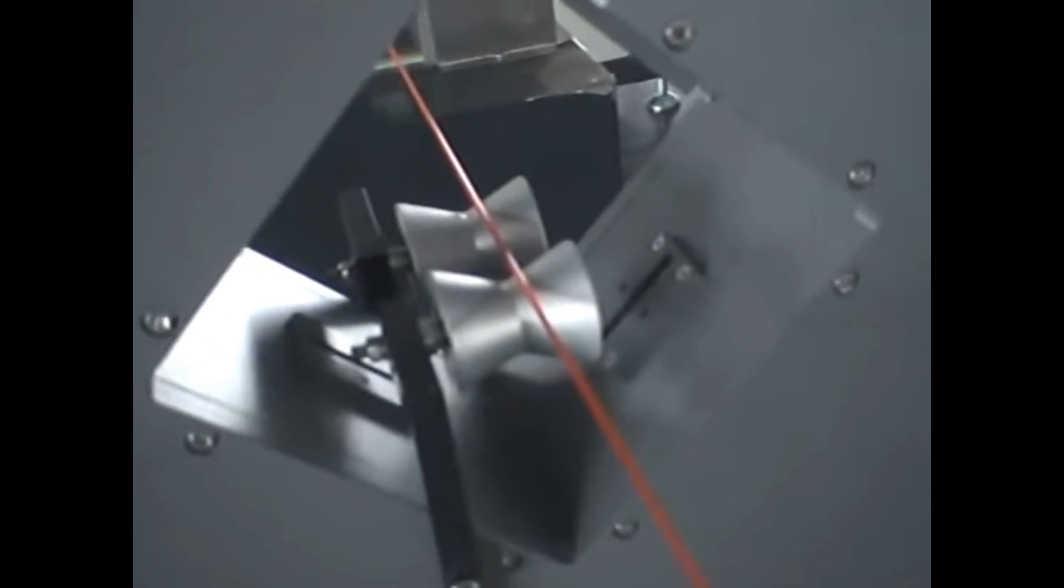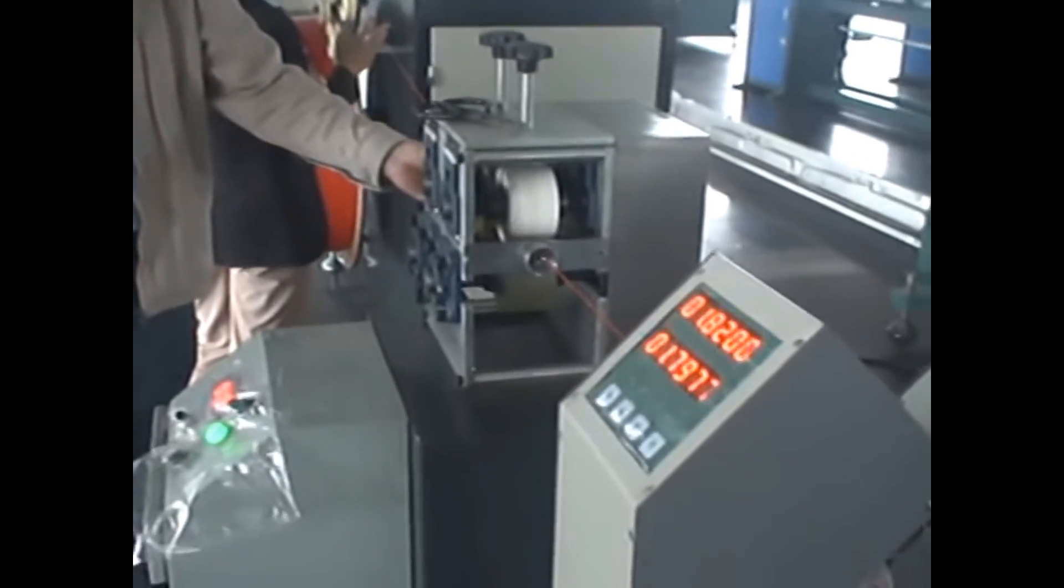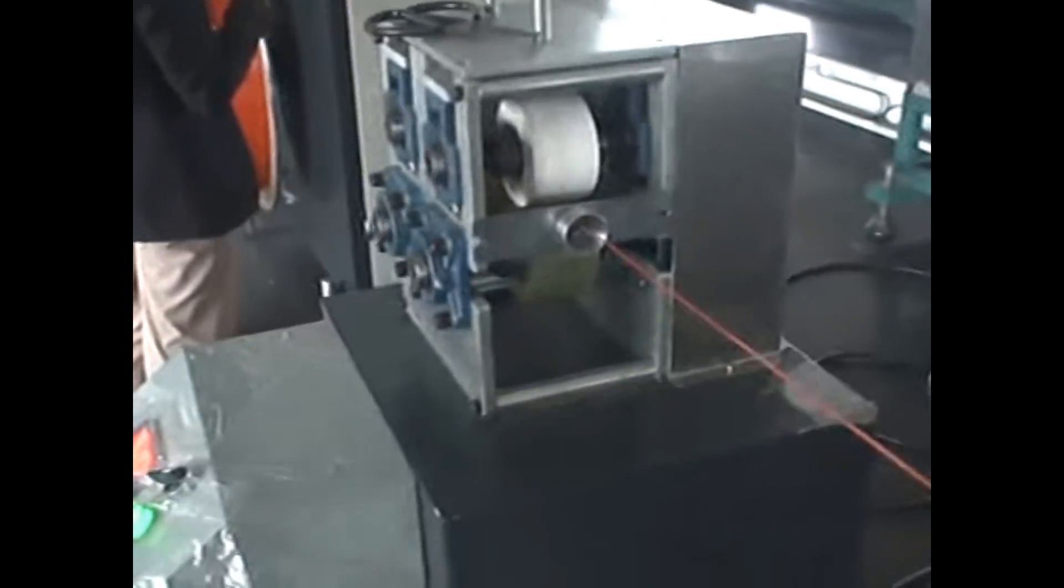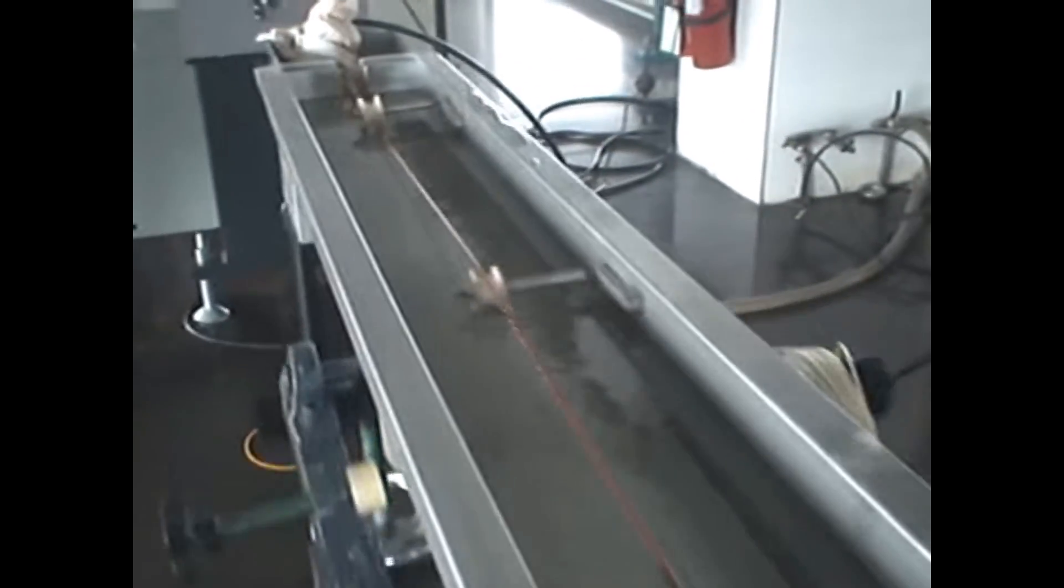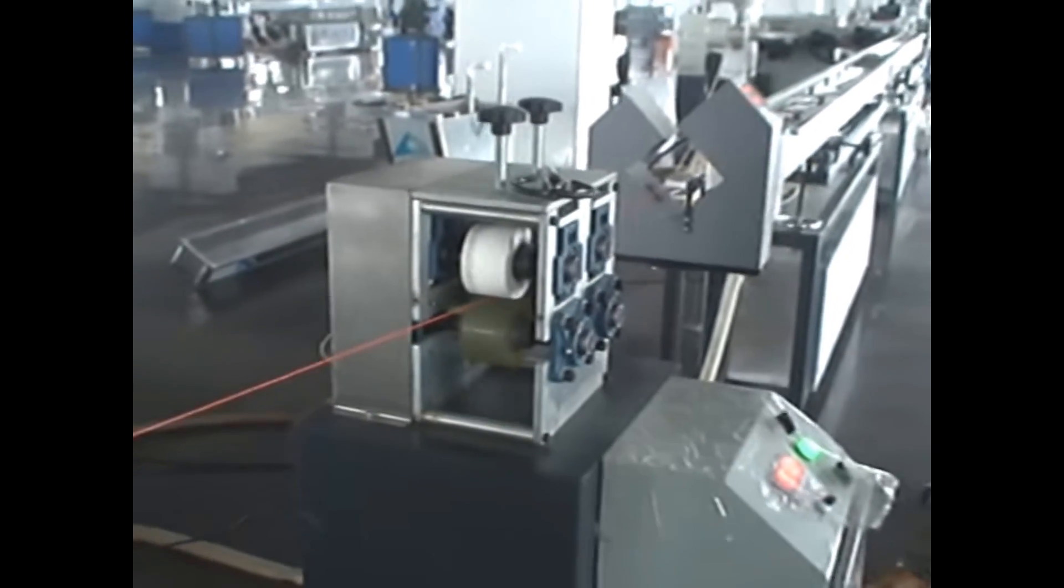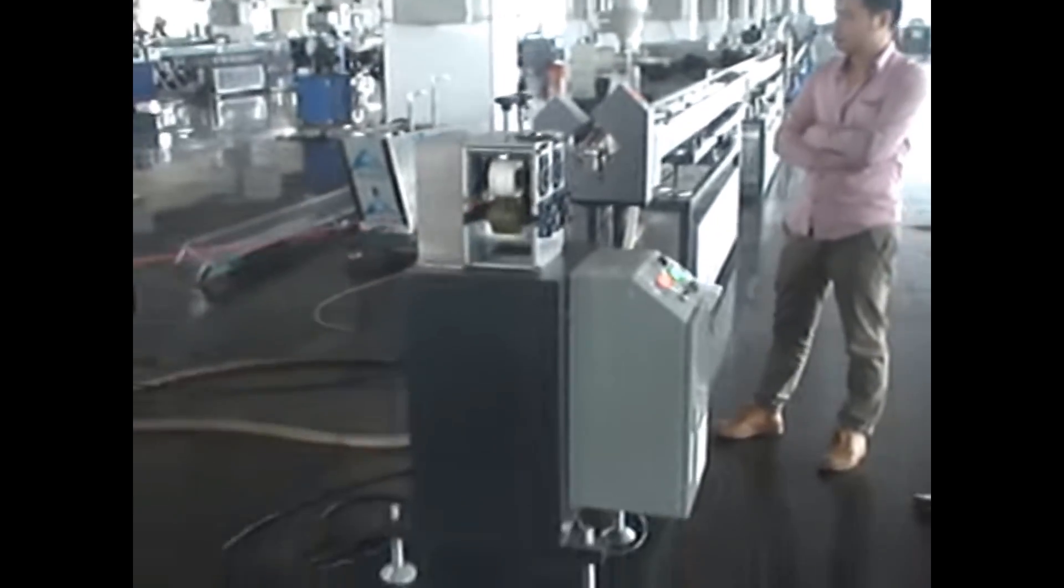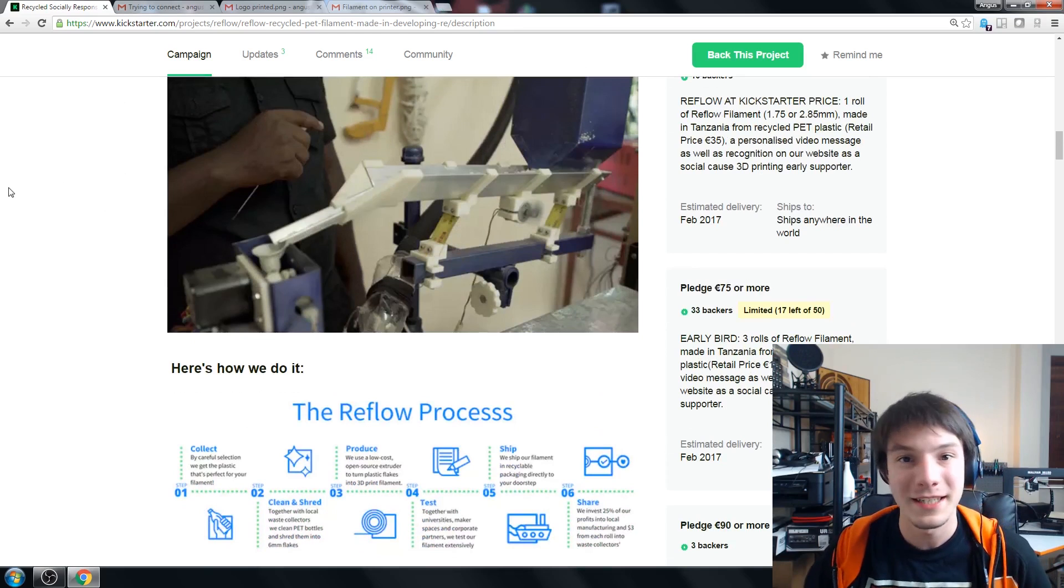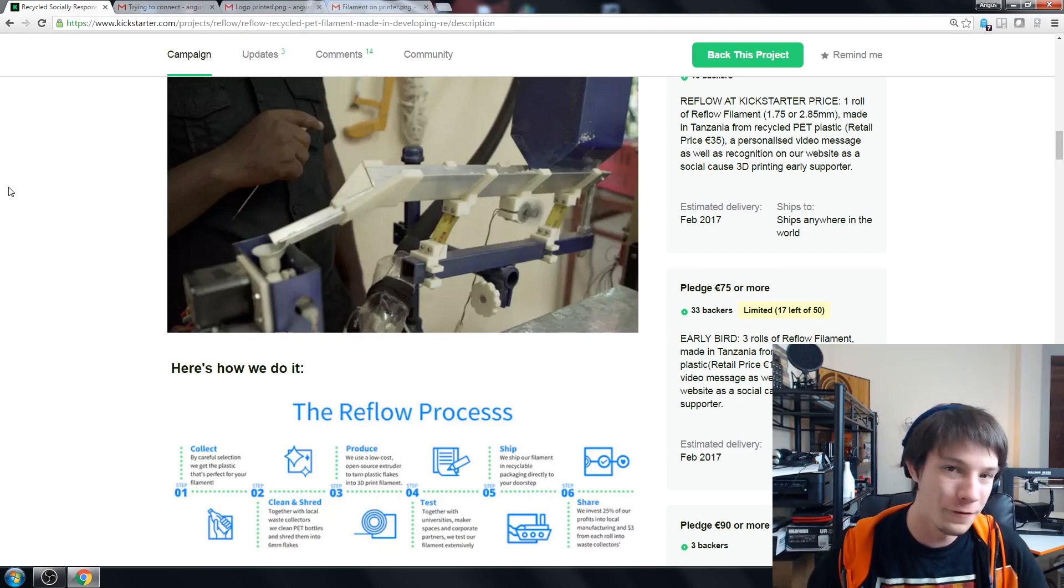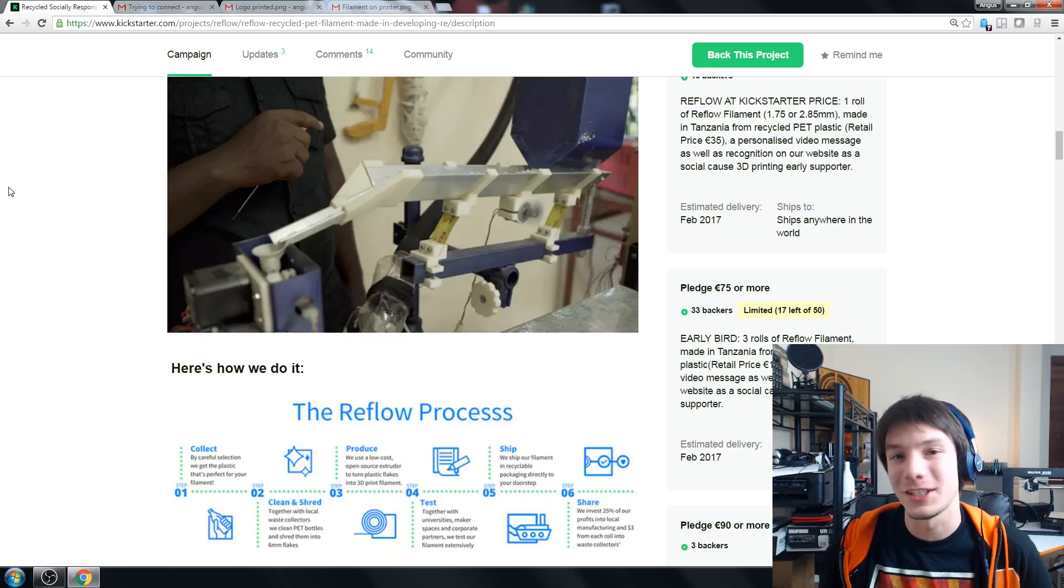So to keep this consistency they will measure it with lasers across two axes and change the filament extrusion pulling speed depending on that diameter. They'll also run it through water baths that cool the filament uniformly and quickly and those water baths are at certain specific temperatures to cool it down not too fast and not too slow. Different types of plastic need different speeds and different water bath temperatures, different orifices and different everything. The parameters change.